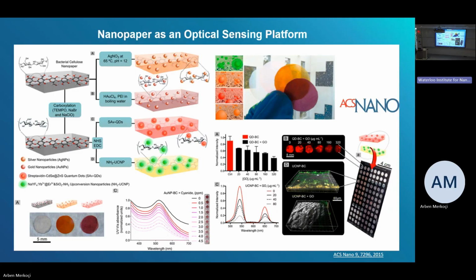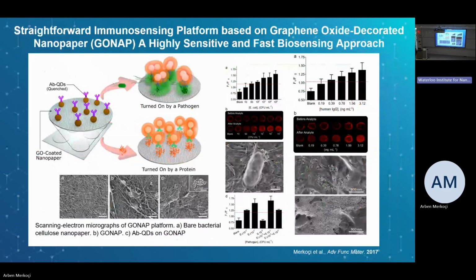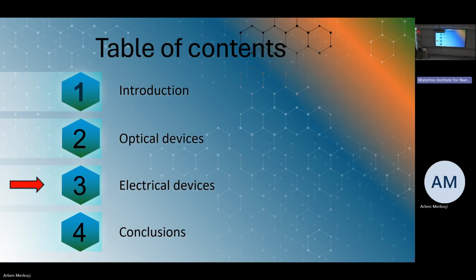So then we correlate this with antibodies. The same operation principle, but now driven by antibodies. And we use the same operation principle to detect some bacteria. So we did the comparison and control of different other bacteria, and we found out that it was a very simple device that can show, with the same operation principle, just by dipping and checking the change of the color, the presence of bacteria in water.